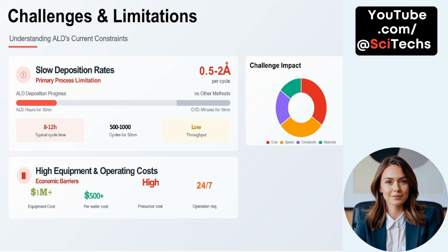Challenges and limitations. Atomic layer deposition provides unmatched precision, but it comes with critical limitations that must be understood. The primary challenge is slow deposition rates, only about 0.5 to 2 angstroms per cycle. To deposit a 10 nanometer film, it can take several hours, whereas other methods like chemical vapor deposition complete similar tasks in just minutes. For a 50 nanometer layer, ALD may require between 500 to 1,000 cycles, translating to 8 to 12 hours of typical cycle time. This results in low throughput, making ALD less ideal for high-volume manufacturing without optimization.